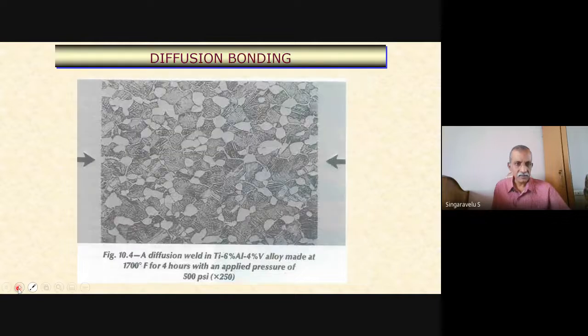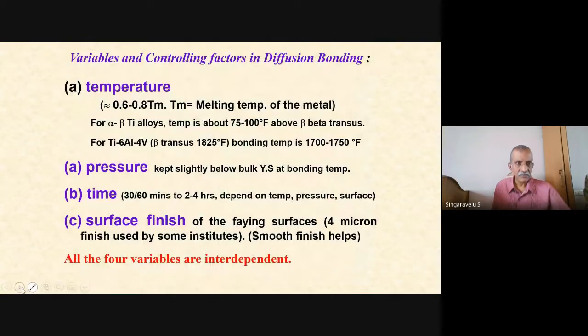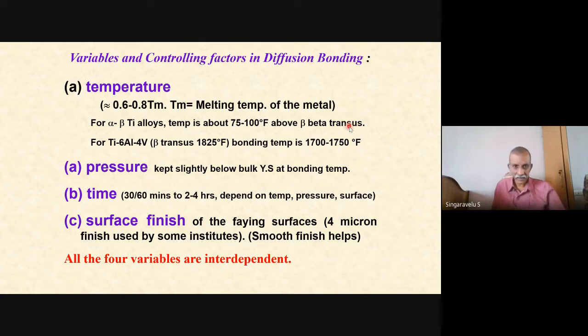Structure, skip that. The temperature is almost 0.6 to 0.8 times the melting point, right? This is what has to be done. For alpha-beta titanium alloys, it is 75 to 100 degrees Fahrenheit above the beta transus. Transus is nothing but the critical temperature. In the iron carbon diagram you have seen a lower critical temperature, upper critical temperature, and so on. Here it is only one, alpha to beta. The temperature is called the beta transus. It is always 75 degrees Fahrenheit above the beta transus temperature.